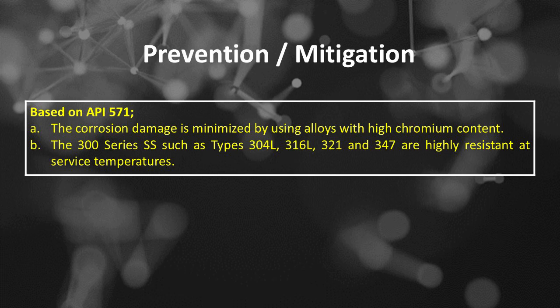High-temperature hydrogen or H2 and hydrogen sulfide or H₂S corrosion prevention and mitigation based on API 571. Number A, the corrosion damage is minimized by using alloys with high chromium content. Number B, the 300 series SS such as types 304L, 316L, 321 and 347 are highly resistant at service temperatures.